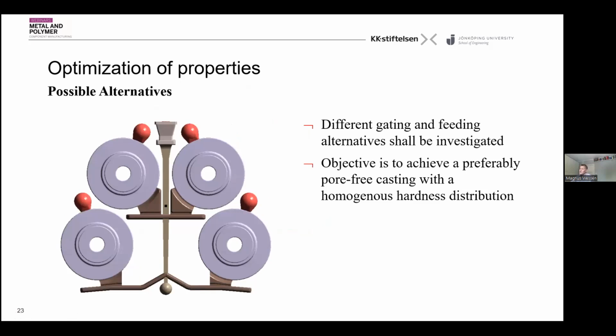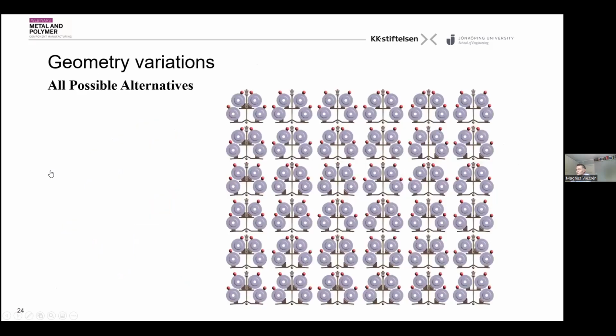So in this case, the foundry was trying to find the most optimum design of the gating and the feeding to minimize the amount of porosity, and also to minimize the variation in hardness inside the brake disc. If you have a hard area here and a soft area here, that will cause vibration and other things. So this is a nice case where you mix two different kinds of objectives which are not related to each other, but it's good to find the best design.